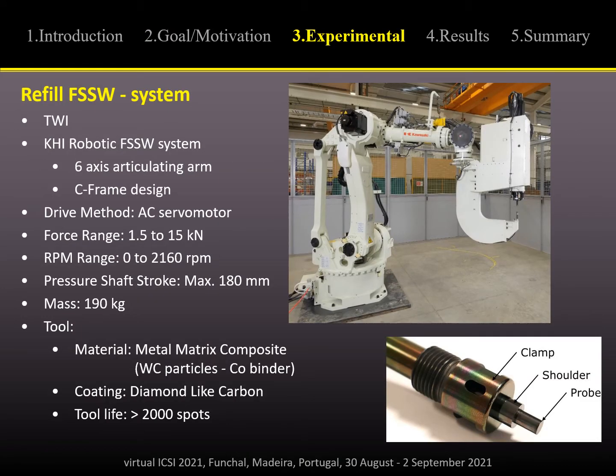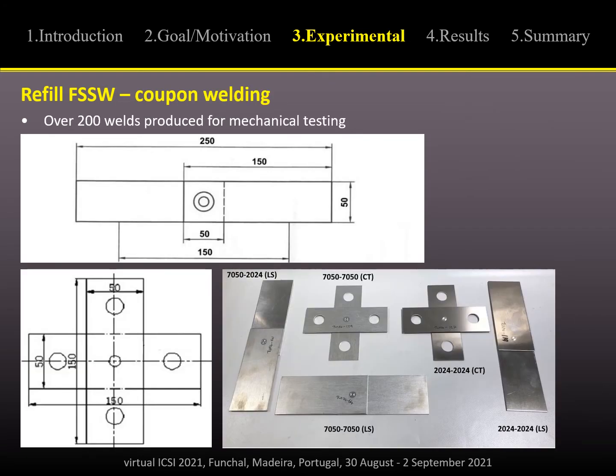All refill friction stir spot weld trials were done at TWI using this Kawasaki robotic system with a 6-axis articulating arm and C-frame design, with a force range up to 15 kilonewtons. And the system was equipped using this tool made of metal matrix composite with a diamond-like carbon coating. By this method, over 200 welds have been produced for mechanical testing in the form of lap shear test samples, shown here, and cross tension samples.